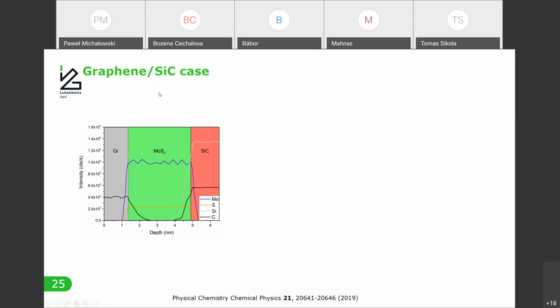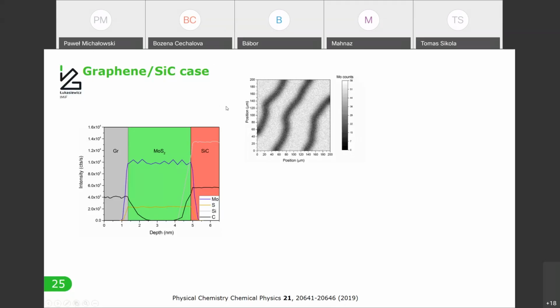This was kind of surprising, but we assume that the explanation is that the silicon carbide has step edge structures with some edges and terraces, and it is well known that at the step edges some material can intercalate the graphene. So we repeated the measurements only with molybdenum, and so we deposited some molybdenum on graphene and heated up, and we saw that at the very top, at the surface, there is some depletion of molybdenum corresponding exactly to the step edges of silicon carbide.